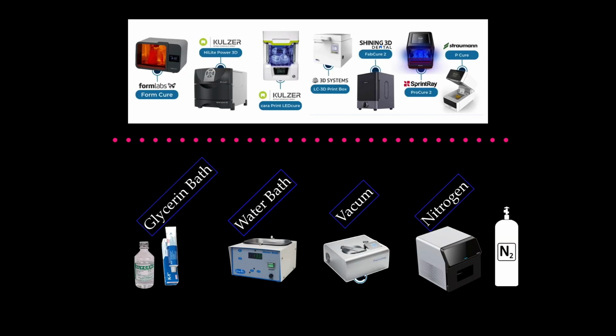Dr. Ahmed Hassani and IDD made a very nice comparison of different brands and different curing units, and we can summarize the technology or methods we use to cure our 3D printed restoration: using a UV box alone, or we put our restoration in a glycerin bath to make an oxygen inhibition layer for fully curing our restoration. For the same purpose, we can use a water bath light cure, and we can use another light box which works with vacuum technology, a vacuum pump to withdraw the air from the light box, so we can make an oxygen inhibition layer for the final curing of our restorations, or we can use the nitrogen light cure.